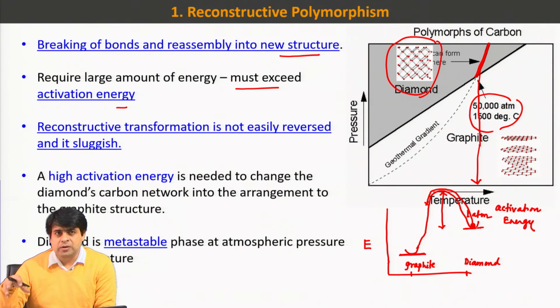If you keep a diamond at room pressure in one place and return after maybe billions of years, you will find that the diamond has changed to graphite. Diamond is a high pressure form of carbon, but because its activation energy is very high, it is stable at room pressure conditions. So, it is called a metastable phase. Similarly, you can find tridymite or cristobalite, which is a high temperature polymorph of quartz, that is also stable at room temperature conditions. Okay.